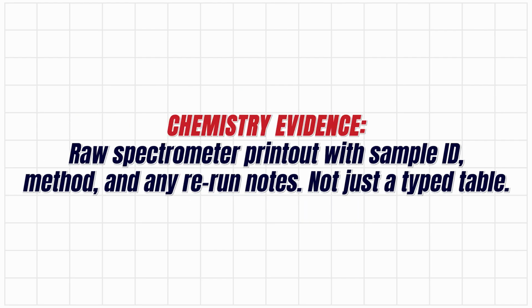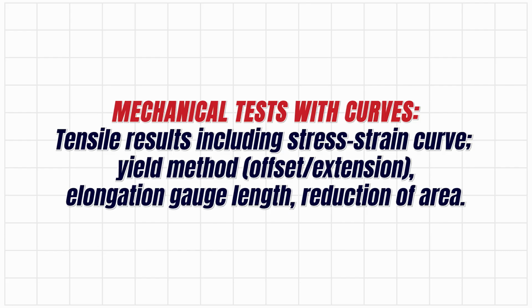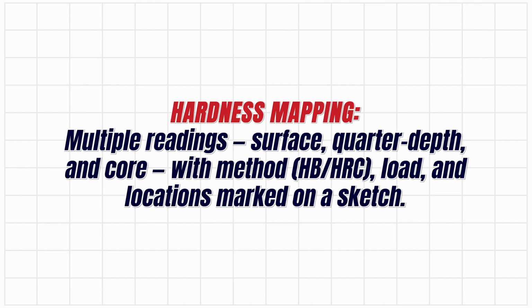Chemistry evidence: raw spectrometer printout with sample ID, method, and any rerun notes, not just a typed table. Mechanical tests with curves: tensile results including stress-strain curve, yield method, offset or extension, elongation, gauge length, reduction of area. Hardness mapping: multiple readings at surface, quarter depth, and core, with method, maybe HB or HRC, load, and locations marked on a sketch.